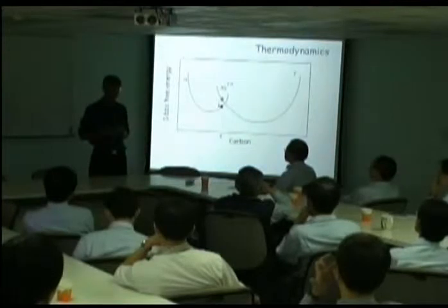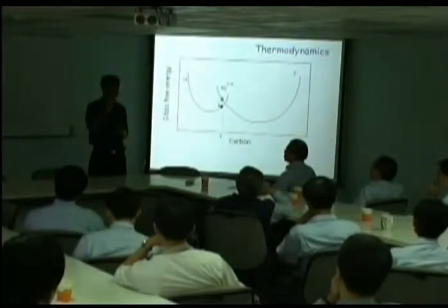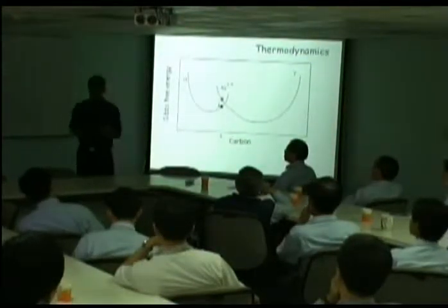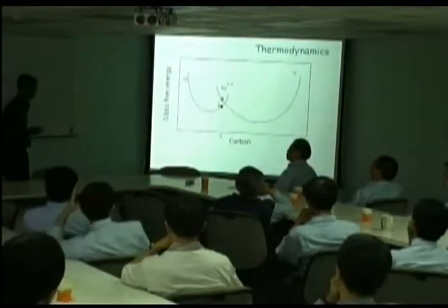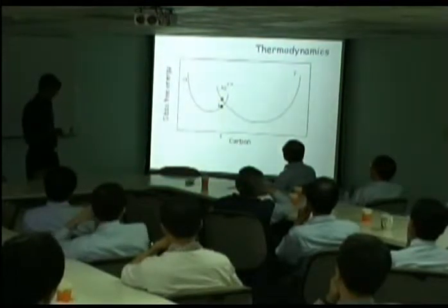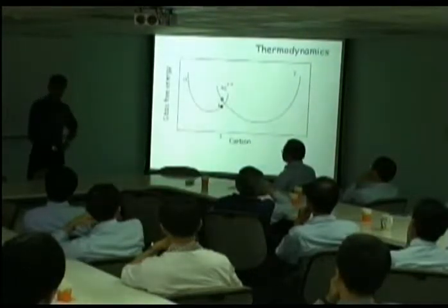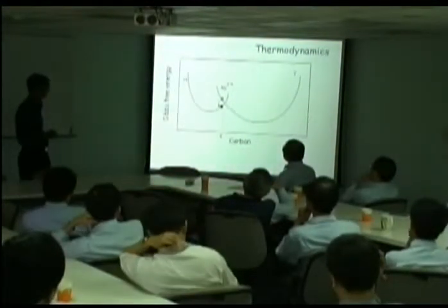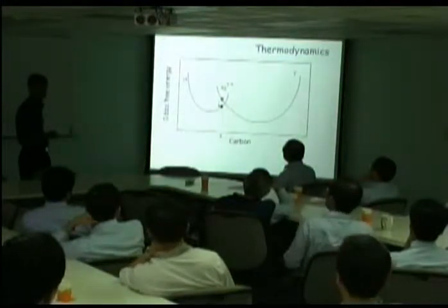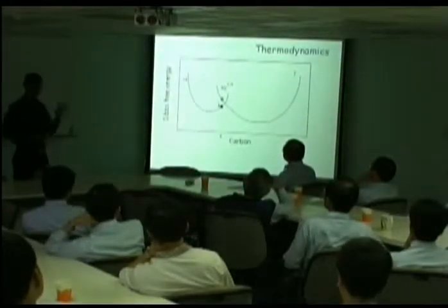And remember that nucleation is a very, very difficult process to study because after all, you're dealing with very, very small sizes and it's almost impossible to observe a nucleation event. But there are things we can do to get quantitative information about nucleation. So again, if I go back to my free energy curves, this is the free energy curve of ferrite and of austenite, and I want to define two terms. First of all, this is the driving force here, ΔG^γα, for diffusionless transformation. So if I go from austenite of this composition to this, this free energy change I will label as ΔG^γα.